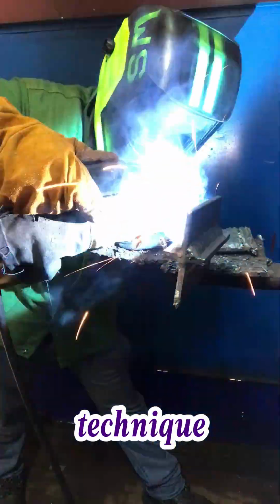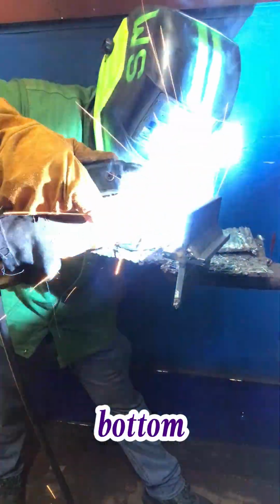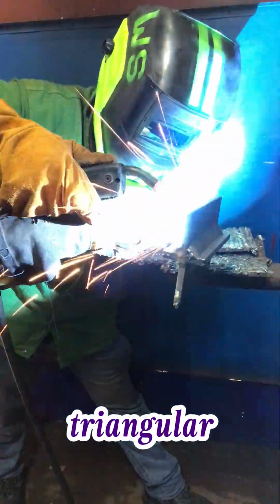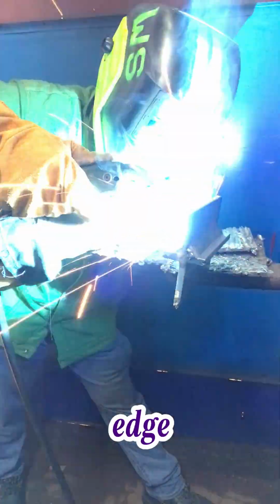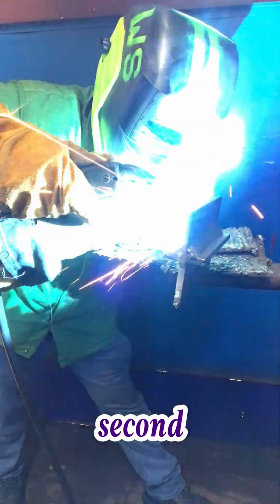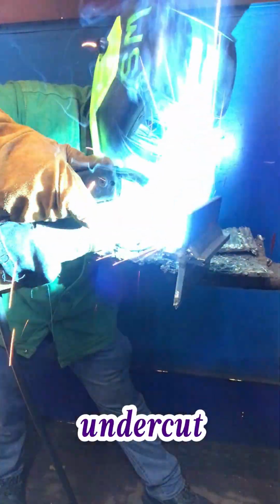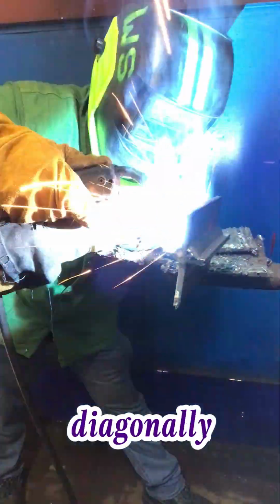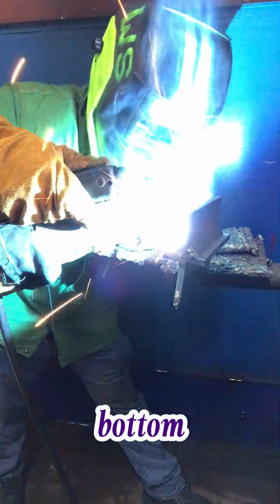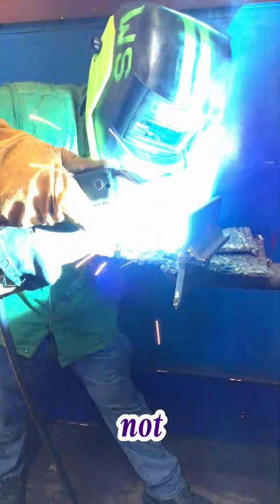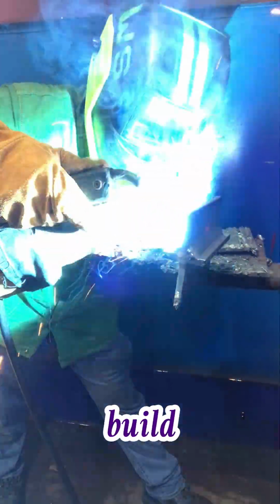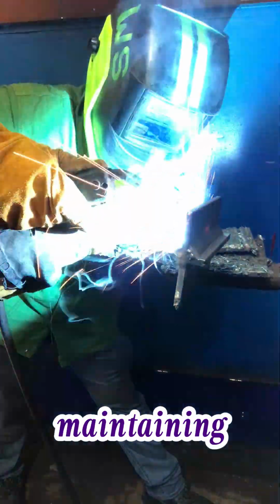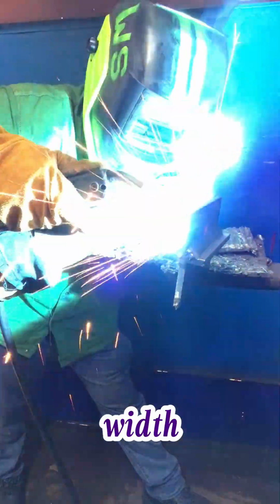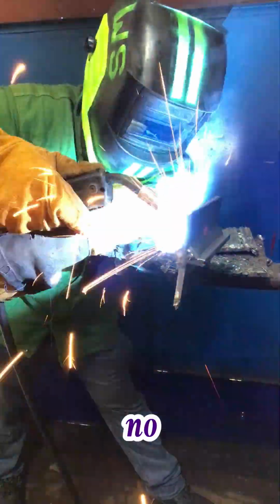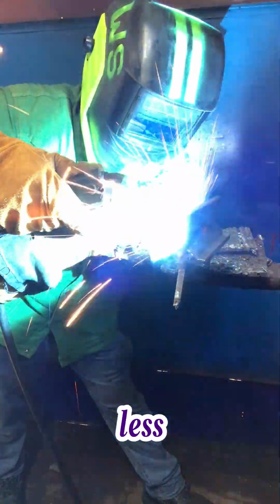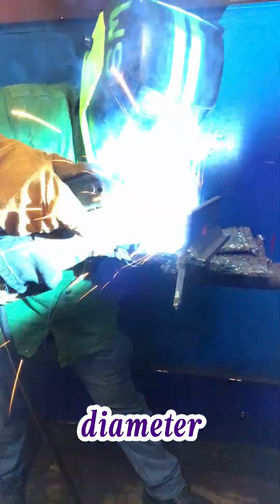Weave pattern and technique: pause top, run bottom. Use a slanted zigzag, triangular weave. At the top edge, pause 1/2 to 1 second. This fuses the upper leg and prevents undercut. Middle, move diagonally downward smoothly. At the bottom edge, move quickly. Do not pause. This avoids sag and extra buildup. Repeat, maintaining consistent side-to-side width and forward speed. No wide weaves. Keep weave width less than or equal to 3 wire diameters.